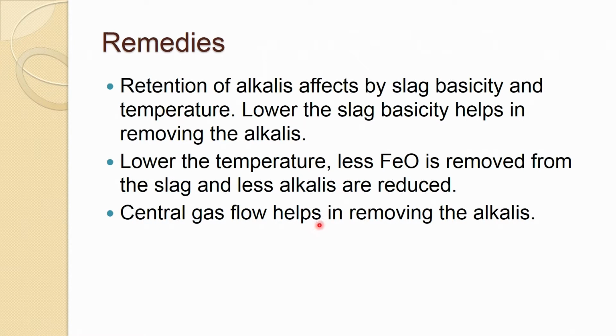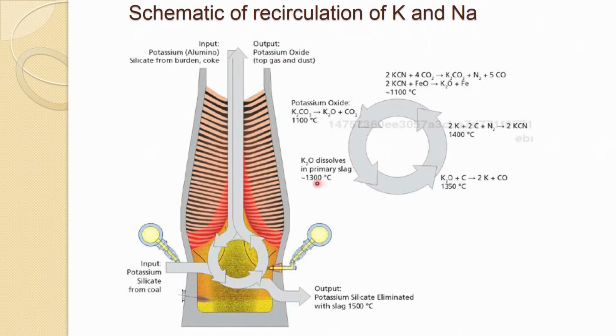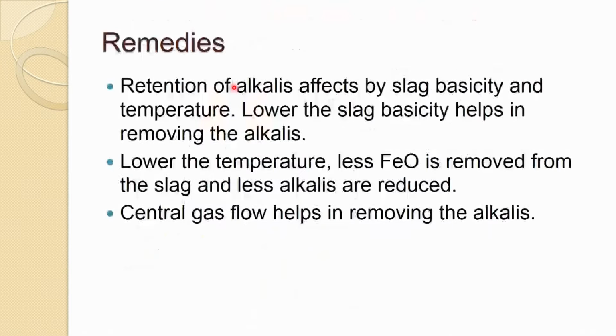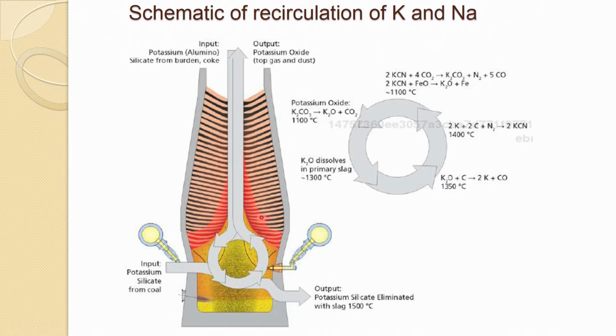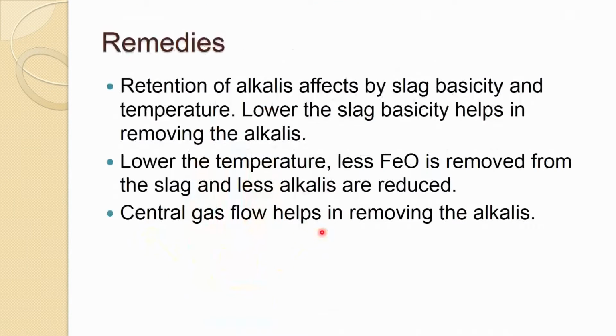And central gas flow helps in removing the alkalis. So, as I mentioned in the previous slide, if it is a central gas flow, by changing the charging and other ways you can achieve this, which we had discussed before, then you may reduce the alkali content in the charge, and thus you can minimize the scaffolding of it.